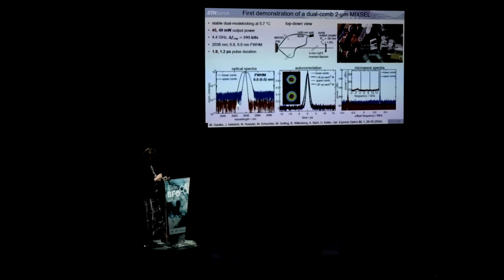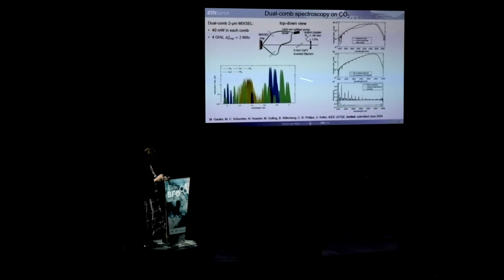And you can see, because the separation of the 2 beams on the MIXSEL chip is like 2-3 millimeters, the uniformity of the chip in this university MBE system is not perfect, but still we had significant spectral overlap of the mode-locked pulse train, and we could actually then use this laser, next slide, to do a first demonstration of absorption measurement of CO2 around 2 micrometer.